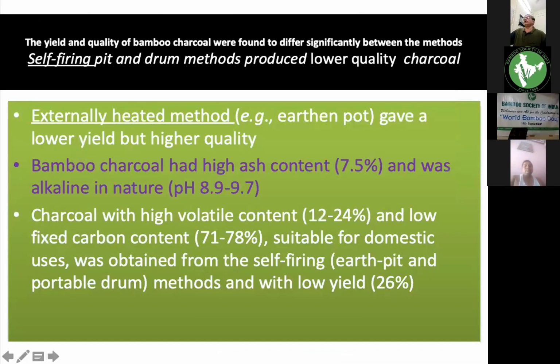Yeah. So here the inference is that the yield and quality of bamboo charcoal were found to differ significantly between the methods. That means the two types of methods we employed, self-firing pit and drum methods, produced lower quality charcoal, whereas the externally heated method, for example the earthen pot we just tried, gave a lower yield but higher quality. And the bamboo charcoal we produced has high ash content, at the rate of 7.5%, and is alkaline in nature with a pH of about 8.9 to 9.7. So it is alkaline and the ash content is a little bit higher.